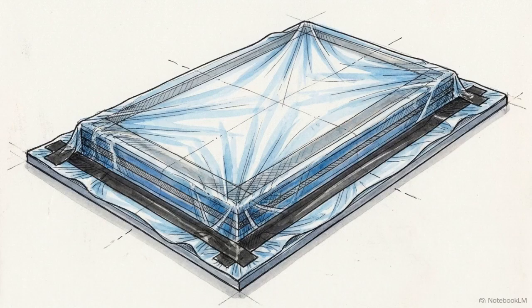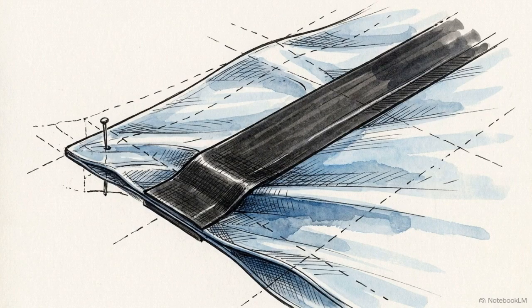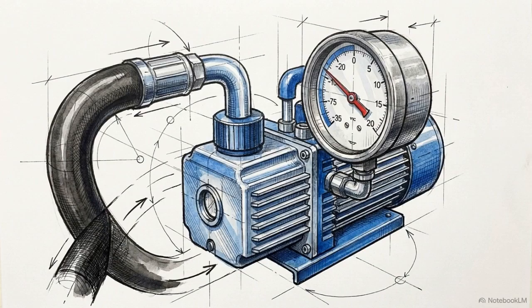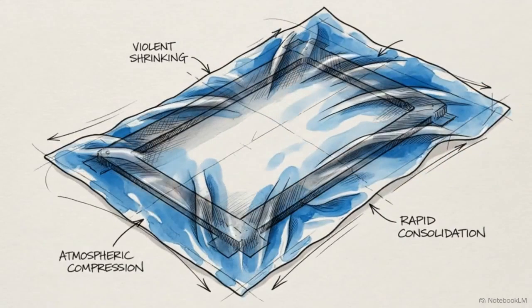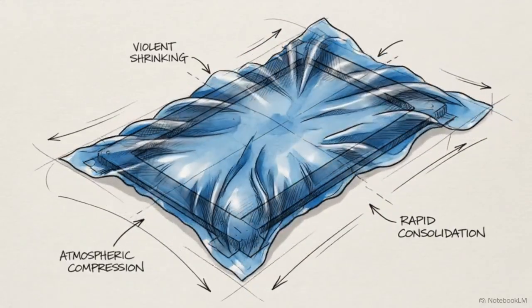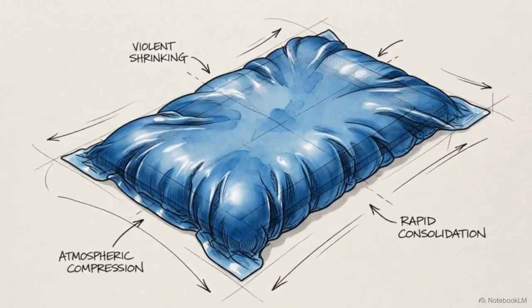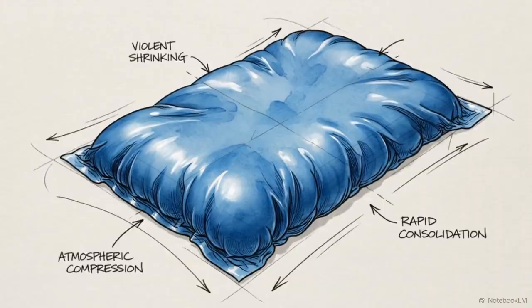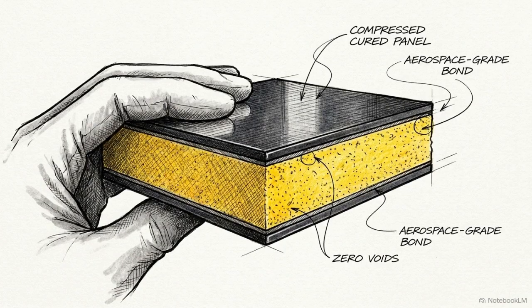Fabricators drape a vacuum bagging film over the entire panel and seal the perimeter with tacky tape. The tape must be perfectly flat. Even a microscopic wrinkle creates a leak that prevents the layers from bonding. Activating the vacuum pump triggers a massive shift in atmospheric pressure. As the air is evacuated, the plastic sheet rapidly shrinks and conforms tightly around the stack, compressing the layers together. This extreme atmospheric compression is what forcefully bonds the layers and squeezes out excess resin, creating a fully consolidated, aerospace-grade